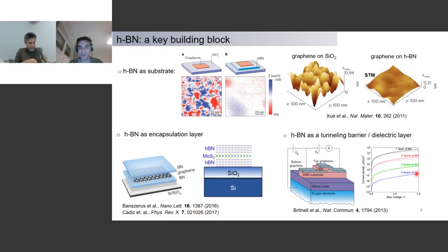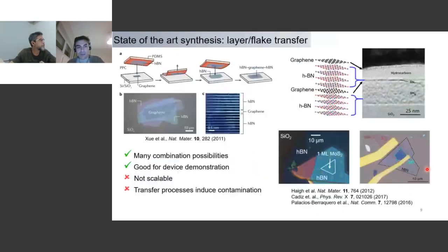And in addition, HBN has been used as a dielectric layer, as a tunneling barrier for more sophisticated structures combining graphene with HBN, for instance, tunneling transistors, where what is nice to see is that you can change the tunneling in HBN logarithmically when you change the number of layers. If you go from one monolayer to 4 layers, you can see this strong modulation in tunneling current. Of course, this opens many perspectives in terms of devices, where by simply changing one atomic layer in HBN, you can see different effects.